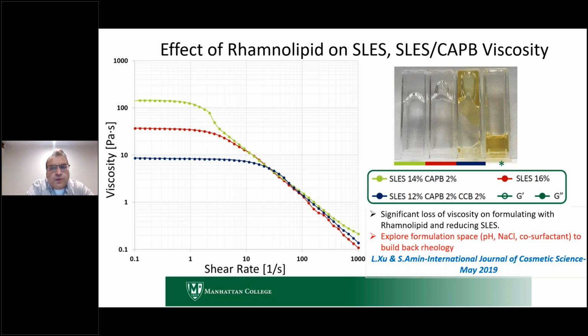But here, what we wanted to do was challenge ourselves: how do I rebuild the formulation, right? What is the experimental design I need in order to explore the variables that are here? Basically, this is a ternary system of 3 surfactants, right? Because you might think, why can't I replace SLES completely with biosurfactant? And you can, it won't build up any viscosity, not for this system. But here we wanted to slowly replace it and see, can we make it at least a little bit more biodegradable?